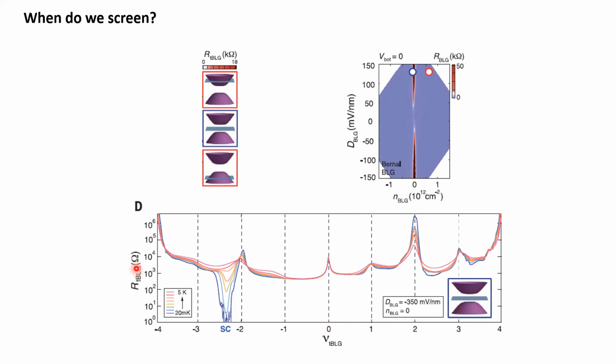This is the resistance for twisted bilayer graphene, while this is the amount of carriers in each unit cell. We can see there are small peaks and large peaks, but there are resistance peaks at the integer fillings in twisted bilayer graphene. We can also see some superconducting region close to a filling of 2 holes per unit cell. So far, so good. These are all old results. Now, the interesting thing is once we go from the insulating case to the conducting case, once we turn on screening.